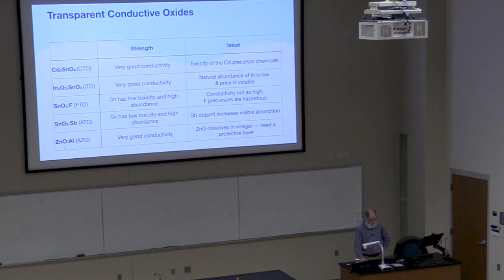And then zinc oxide, very good conductivity, and you can dope it with a couple different things. Unfortunately, zinc oxide dissolves in vinegar. So it could be a really good coating on architectural windows, but you've got to have a good protective layer on there. So you can see nothing's perfect.